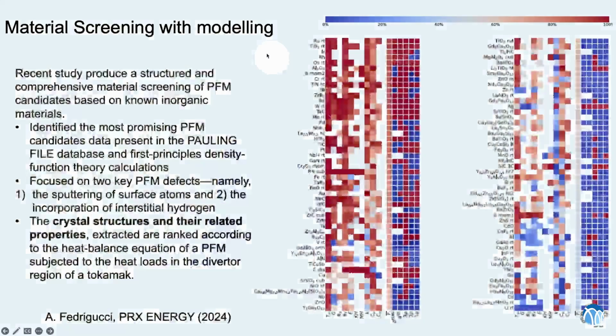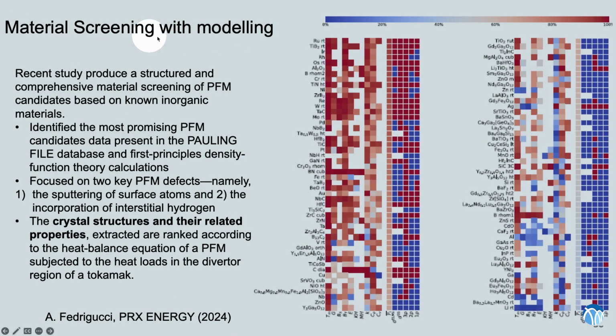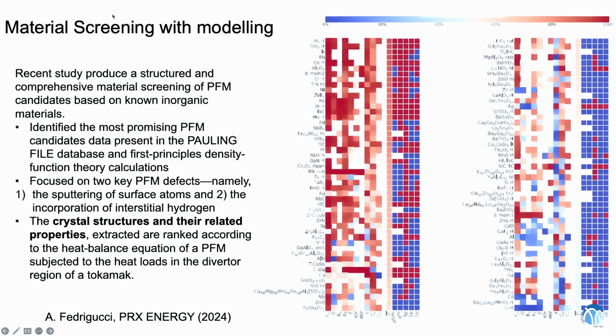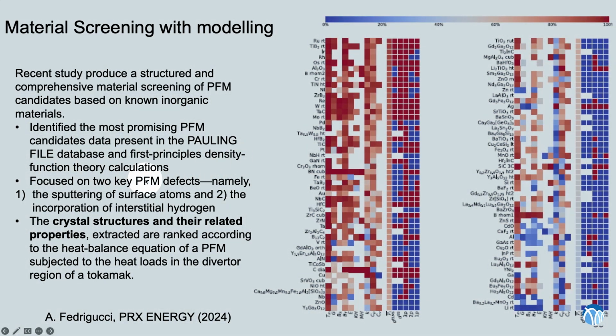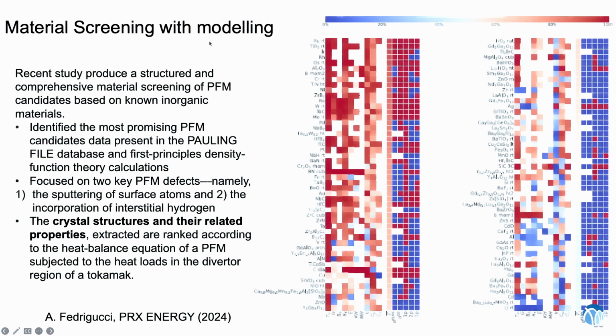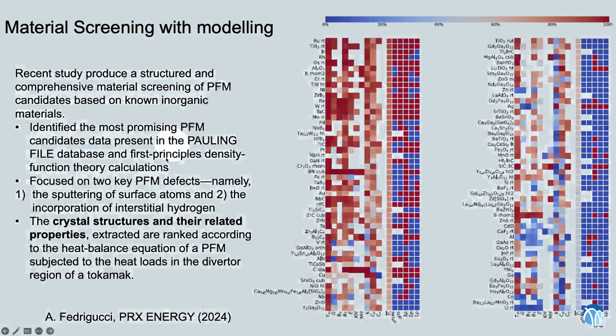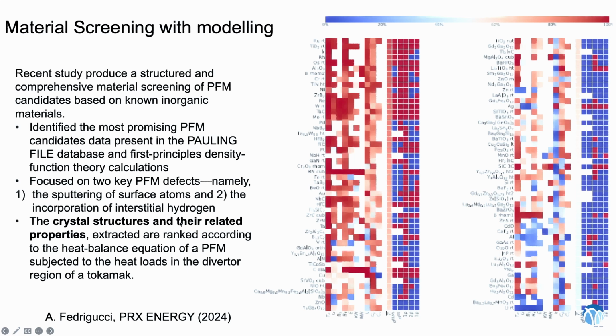This is a lot of data here out of a very interesting paper just last year that took a modeling approach to screening. And what they did was they used a first principles density functional theory calculation to screen through a lot of materials for data that's already there in the database. And they went through a lot of various materials: oxides, carbides, borides, metals. And what they did was they said, well, we know a lot about these materials. We know their crystal structure, and therefore their electronic structure. Let's do calculations specifically screening for two different problems, namely sputtering, so how much material can possibly come off, and the other is incorporation of interstitial hydrogen, so how much hydrogen might be able to be trapped, and we talked about why that is a problem.